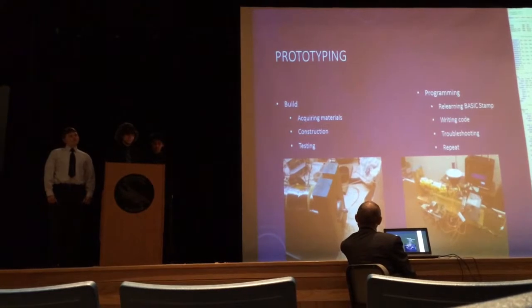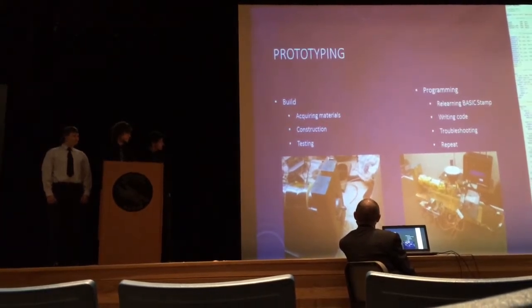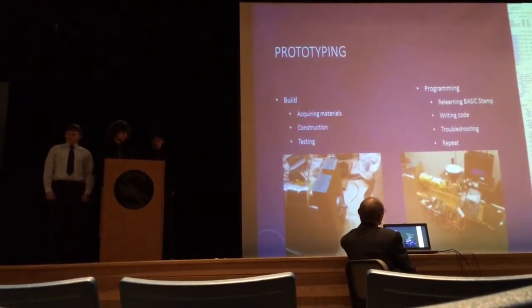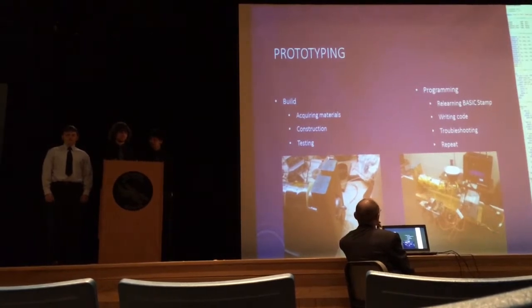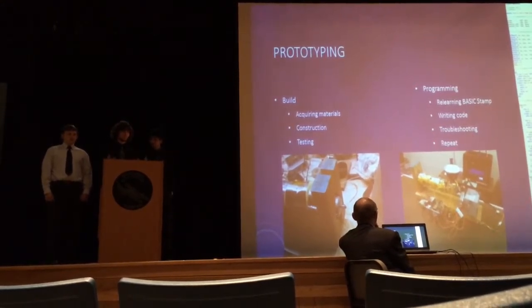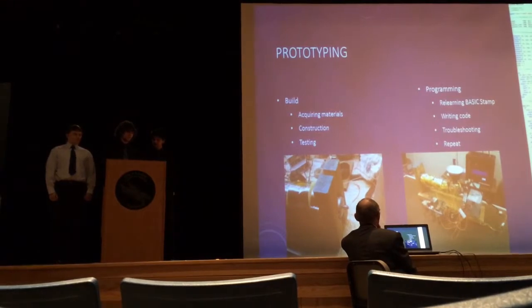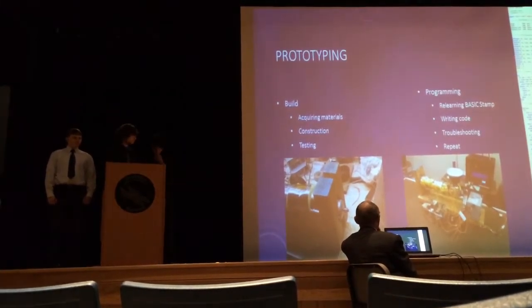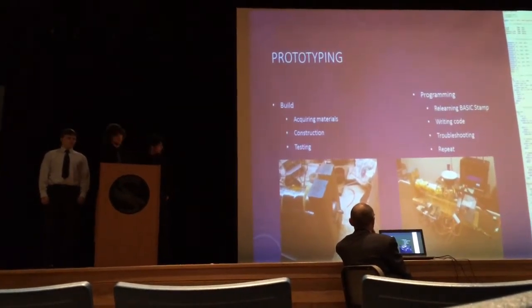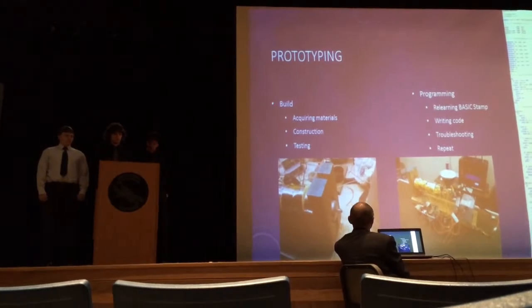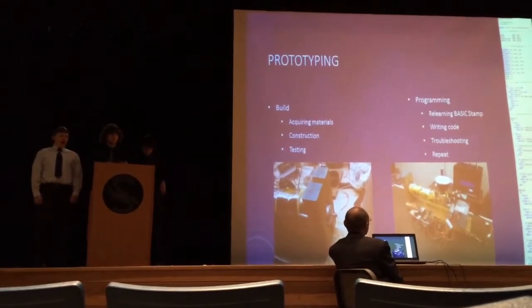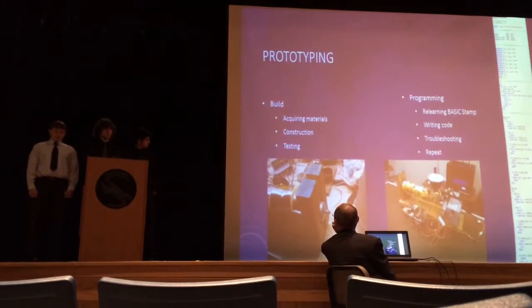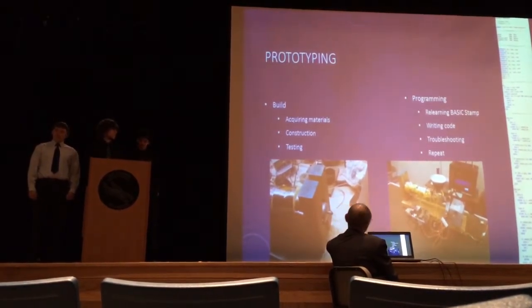It took a long time. And then, of course, there was testing, and that was trying to get everything to heat up when we wanted it to heat up, however much we wanted it to, and a lot of trouble came with the auger, actually, to get it to extrude properly and with enough torque to move all of the plastic that we're dealing with.